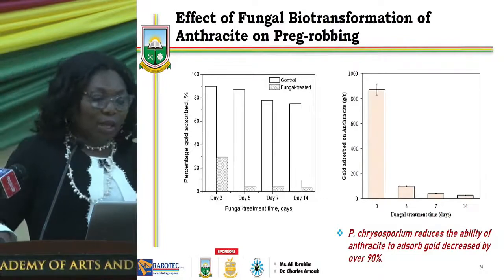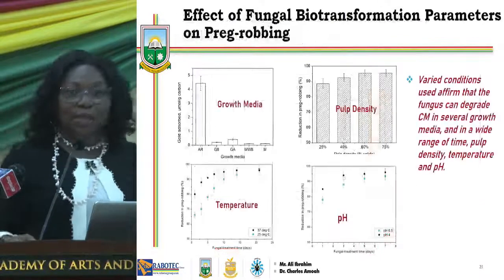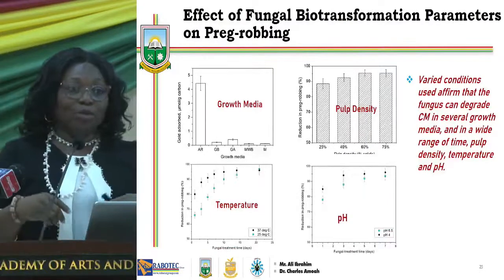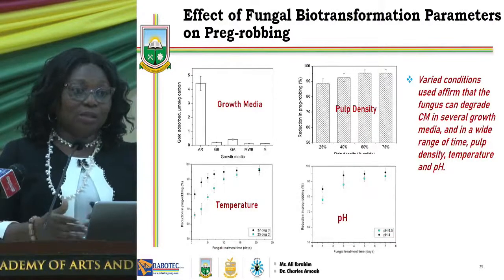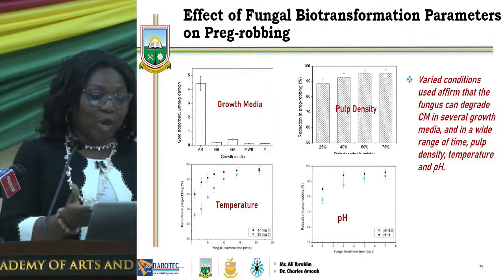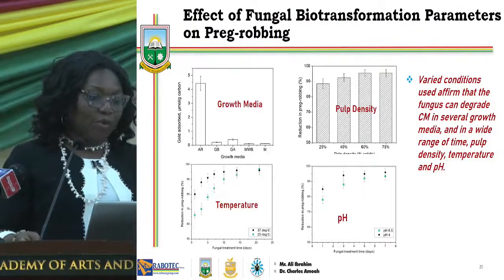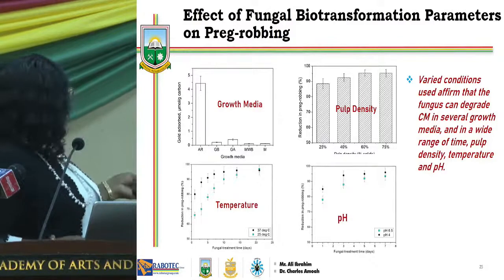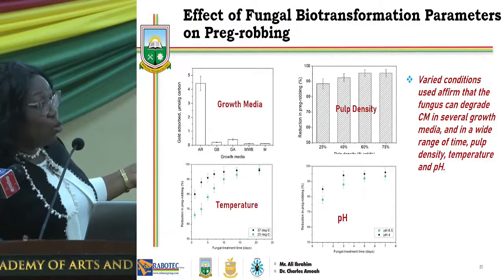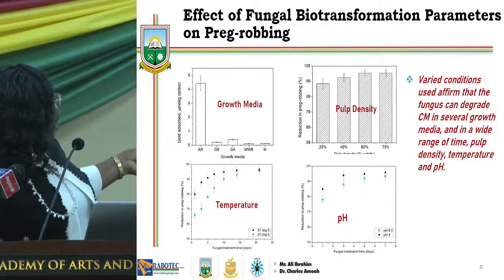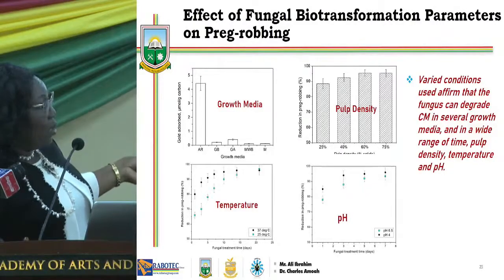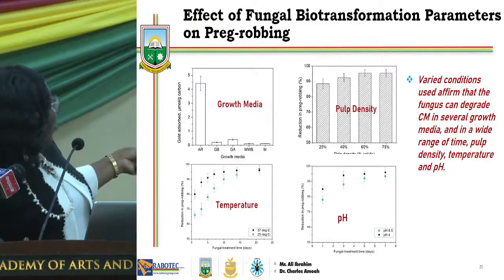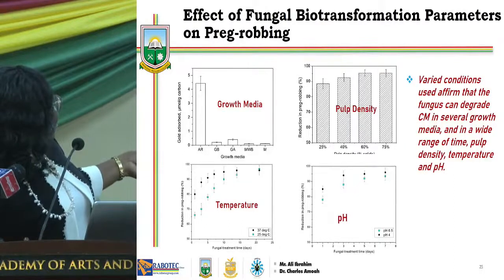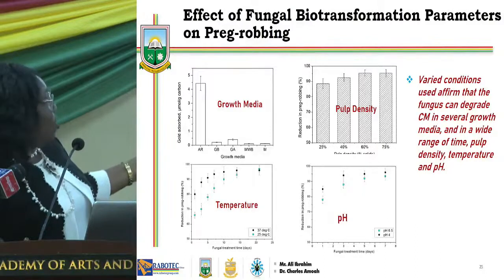These are simply showing us that the fungus can be used in several growth parameters. For example, in this diagram, we are showing different growth media. The first bar is showing the as received anthracite, how much it can absorb. And the rest are all different growth media, and they are able to reduce the amount of gold that can be absorbed on the carbon.